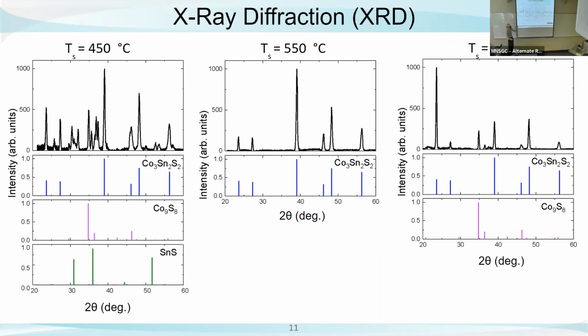And then as we get hotter, we see that those impurities start to go away and we have purely shandite, which is exactly what we wanted. And then if we heat back up, some of those impurities start to come back. And so we see that we've optimized the film growth at 575. And now that we've done that, we want to grow more of them so that we can do magnetometry and transport. That's all for my thin films.